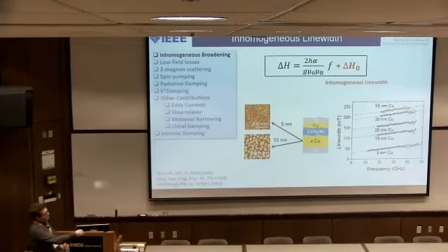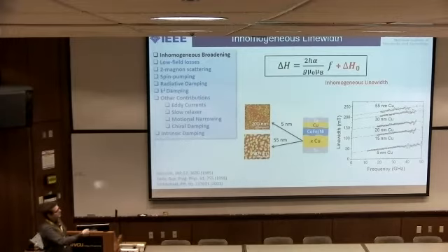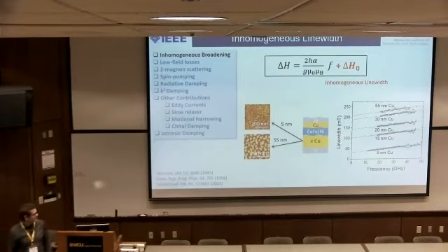Then if we measure line width versus frequency as a function of copper thickness, we see that the offset increases as we introduce more roughness into the system. But you can see by eye that the slopes are pretty much the same, meaning this value of alpha does not change much in this case.